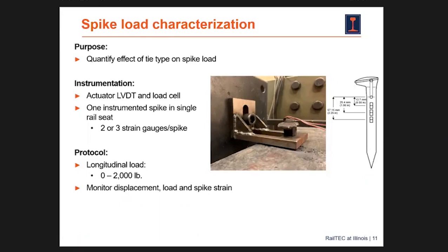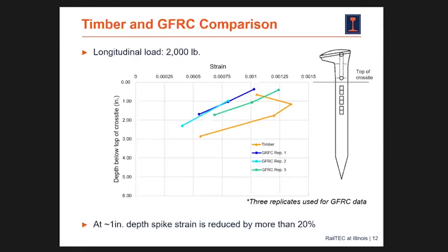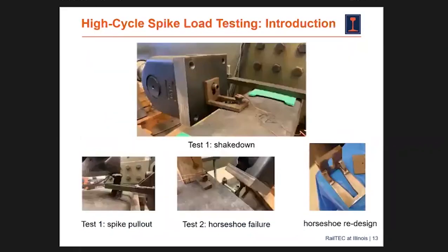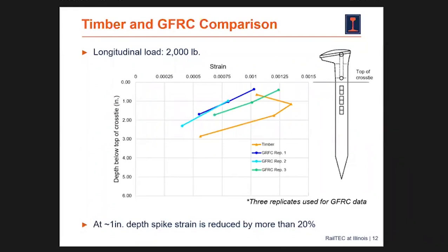And so we took an instrumented spike, drove it into a composite tie and timber ties, and started comparing the strains to one another while applying a longitudinal load to that spike. And I'm just going to throw up the strains. The strains are each of these individual dots that came from our instrumented spikes. We're looking down into the depth of the spike and comparing it to timber, which is in this orange, and all of the composites that we tested, the GFRC ties, replicates that we had are in the other colors. And we can see that at our inch or inch and a half, we have a 20% reduction in strain. So immediately we see that there is a benefit. There is a reduction in strain in the spike when we're installing it into a composite tie with a high strength.